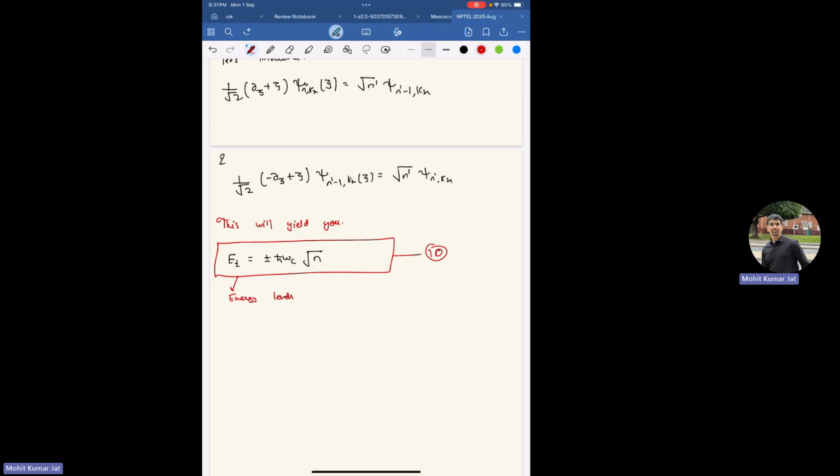Energy levels of graphene, Landau levels. Yeah. So the point to note here is that for graphene, your Landau levels are plus minus, so they can be positive and they can be negative in energies. But for your two-dimensional electron gas, they are always positive, h bar omega c (n plus half). That's the one key difference. There, your Landau level goes linearly with n, right? But here, the Landau level goes as the square root of this quantum number n. So there is another difference.